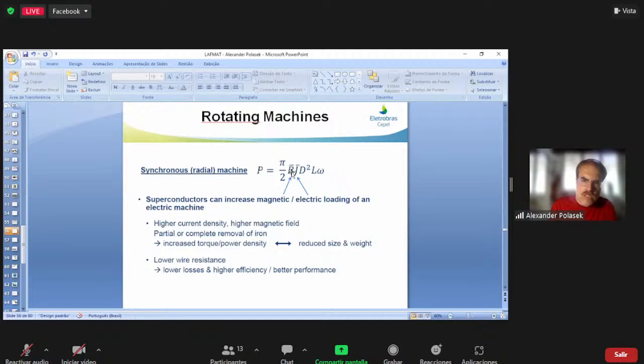Power is dependent on the magnetic field, on the current density, and on other factors. And with superconductors, you can increase the magnetic field because you can have a much more dense magnetic field because of the high current densities. And so you can have higher current density, higher magnetic field, and partial or complete removal of the iron core. And you can increase torque and power density, reduce size and weight, and lower wire resistance.